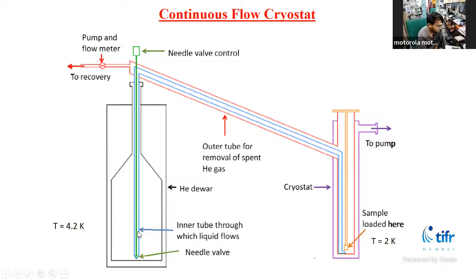Helium flows from this tube via this small cryostat, where the helium is at 4.2 Kelvin. But by pumping over the liquid helium, we are basically minimizing the vapor pressure by lowering its boiling point. That's how it can go to 2 Kelvin. So from room temperature, we can go down to 2 Kelvin to do our measurement and to check the TC of the superconductor between 300 and 2 Kelvin.